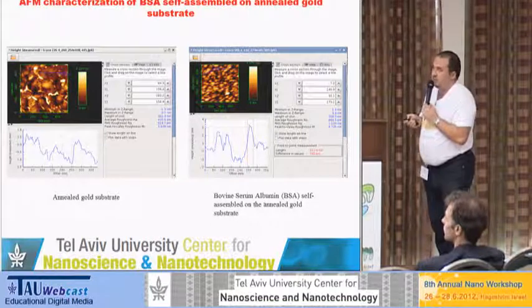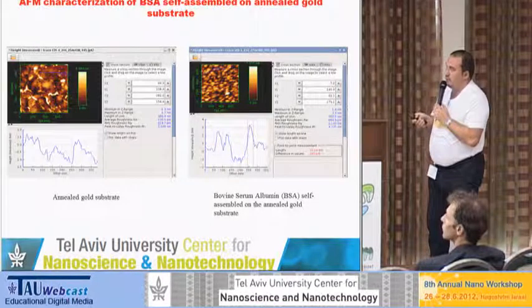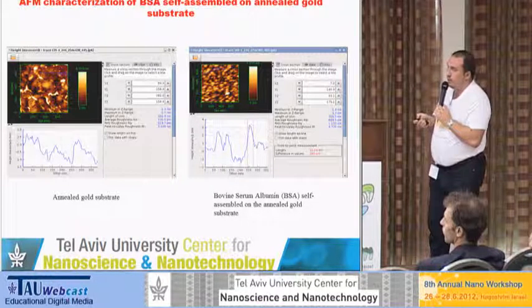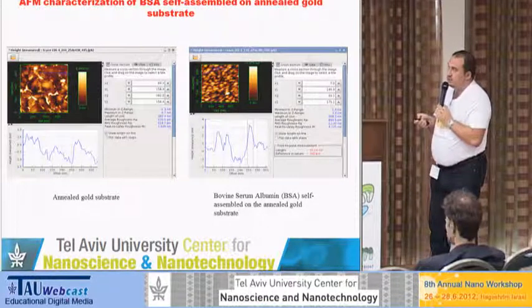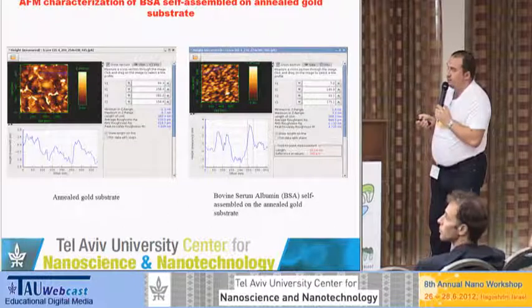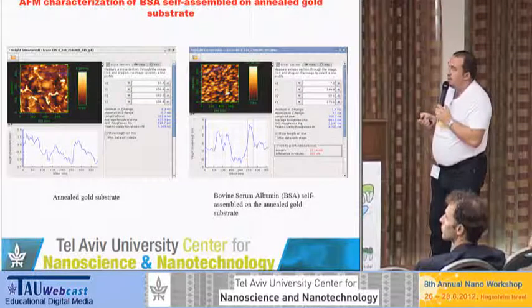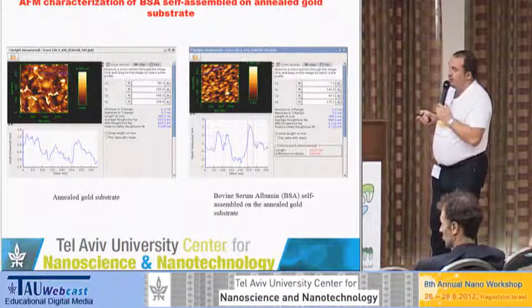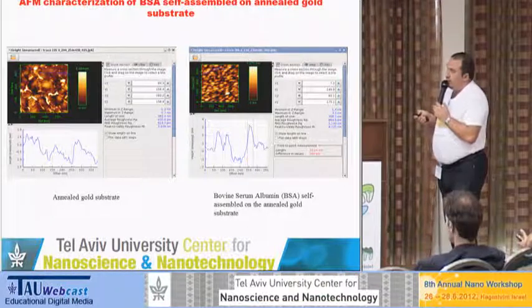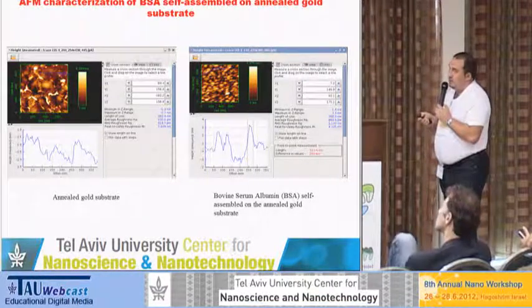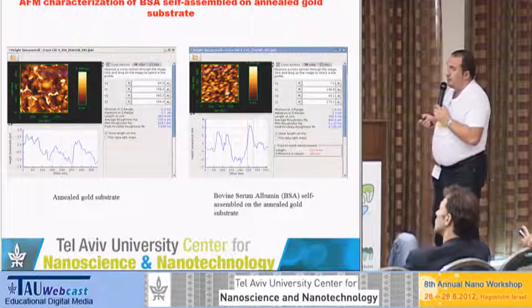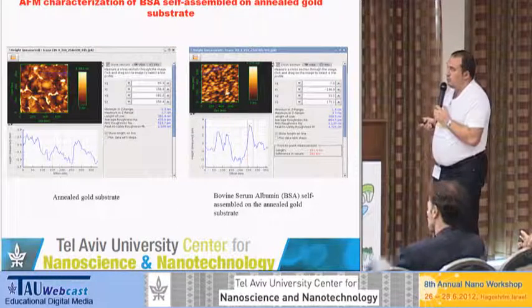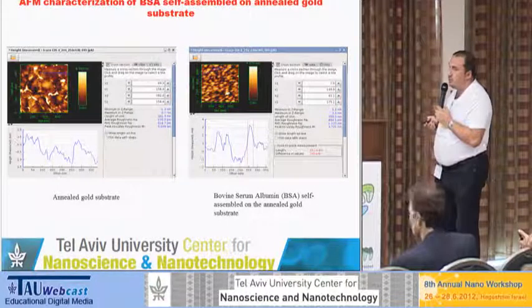And also you can see that if you take, for example, a line profile on the region where the annealed gold is quite flat, the surface roughness here is less than on the BSA sample. And also on the BSA sample we can see features which are quite small. For example, here we could see 30 nanometer.